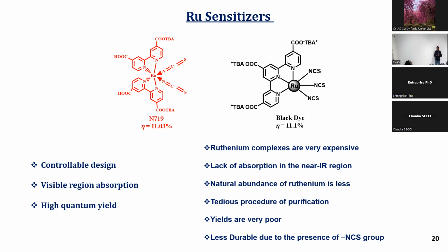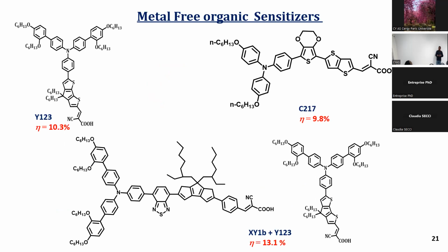Then researchers moved to other, different molecules, which they studied and synthesized. After ruthenium sensitizers, they used small molecules, that is, metal-free organic sensitizers for DSSC. Triphenylamine based molecules with a fused thiophene and the alkyl chain increased from 1 to 3 gradually. The reported molecule reached around 10% efficiency. Another group reported that the triphenylamine based molecule C217 achieved an efficiency of 9.8%.